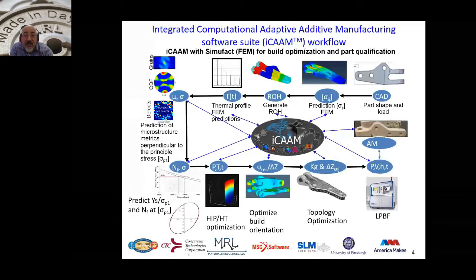Then we feed into our fatigue life prediction models that are able to predict an S-N curve that we validated, and we will show you the validation throughout the process, as well as the anisotropic yield surface in the location of choice. And then we utilize this information to help optimize the orientation of the build itself. Once that's optimized, we have an additional tool to do topology optimization, and you are seeing the part after topology optimization. Then we send it to the machine, which gives us sensor data as well as build information, and then we produce the part and later machine it to specs.